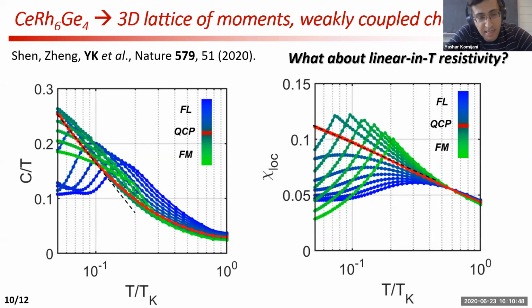Right? And no, of course, this is a major open question, but based on these two examples that I showed you before, somehow I would like to associate the strange metal phase to some reconstruction of the Fermi surface, and therefore also some critical charge fluctuations. And I showed you that in the 1D ferromagnet, there is no jump in the Fermi surface, there is no critical charge fluctuation, but in the anti-ferromagnetic case, we do have it. So it is somewhat puzzling why this ferromagnet shows any linear T resistivity based on that line of thought.